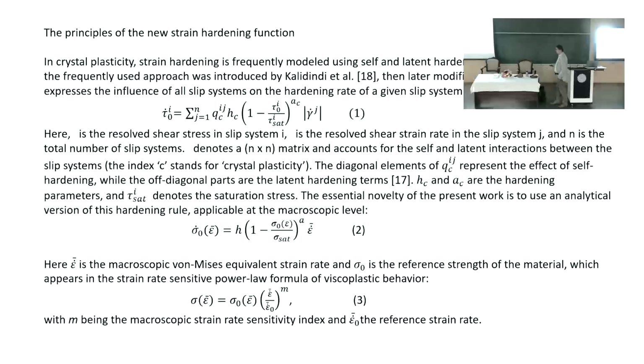So epsilon dot equivalent is the actual strain rate. Epsilon dot 0 is a reference strain rate at which the stress level is sigma 0. So sigma 0 and epsilon dot 0 are connected parameters. M is a strain rate sensitivity index, and this viscoplastic power law is describing very well the strain rate sensitivity of the material.